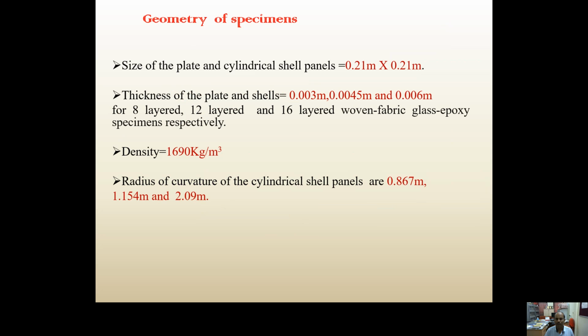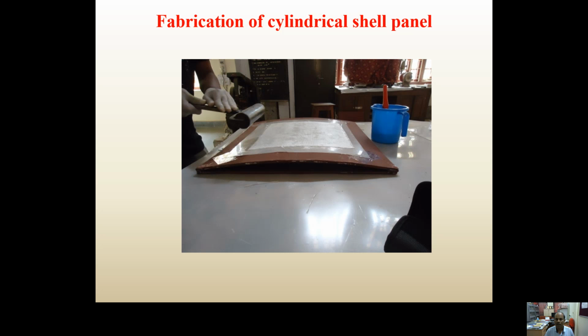Geometry of the specimen: the size of the plate and cylindrical shell panels is 0.21 meter by 0.21 meter. Thickness of the plate and shells is 0.003 meter, 0.0045 meter, and 0.006 meter for 8 layer, 12 layer, and 16 layer woven fabric glass epoxy specimens respectively. The density of the specimens is 1690 kg per meter cube. The radius of curvature of the cylindrical shell panels has been found to be 0.867 meter, 1.154 meter, and 2.09 meter. This is how the fabrication has been carried out.